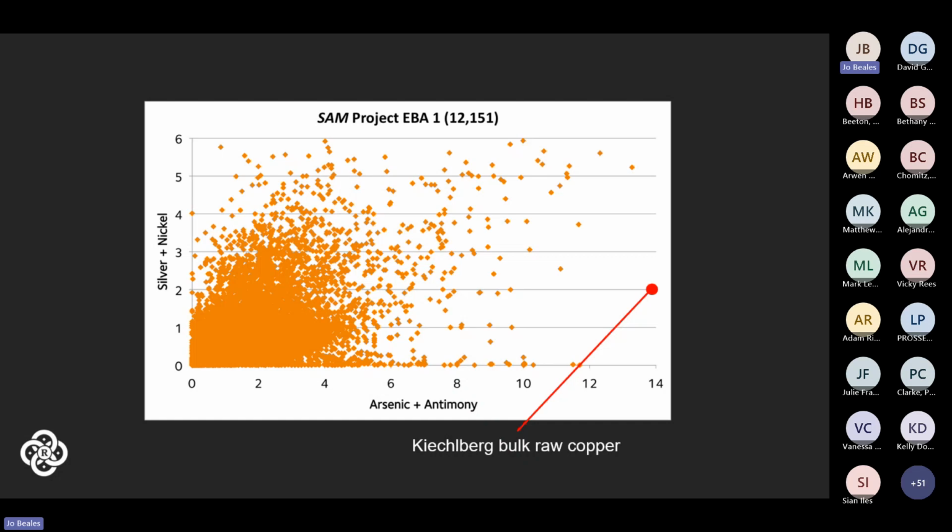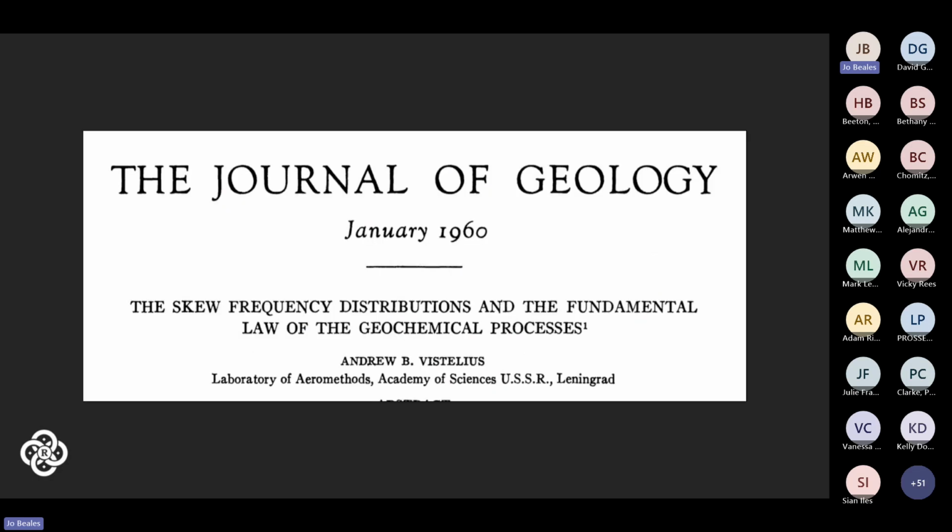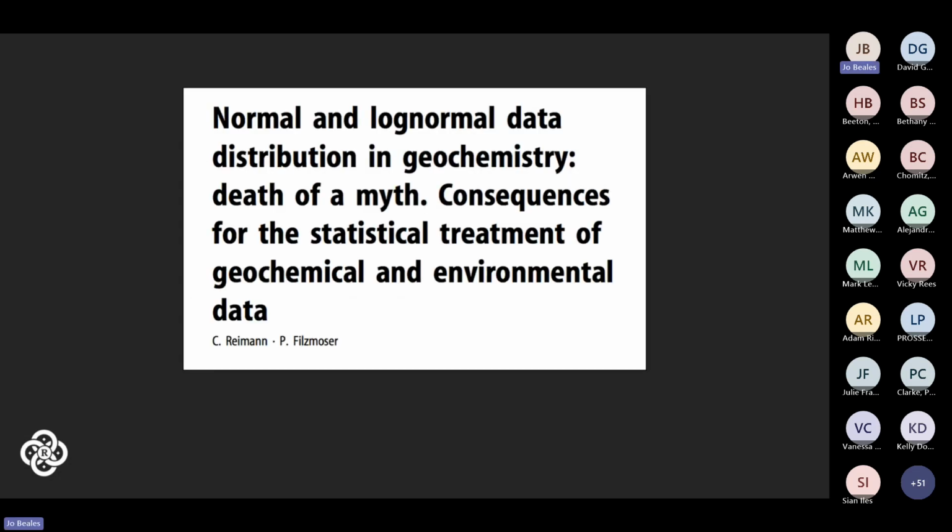So they were picking up billets of pure copper full of impurities and then puddle casting them together to get towards an ingot, and then that ingot was turned into something else. And at each stage, this chemistry is shifting and changing. So if we revisit the fundamental law, it doesn't look as good. And when people actually test the fundamental law, they start to realize, hang on, this could actually be a myth.